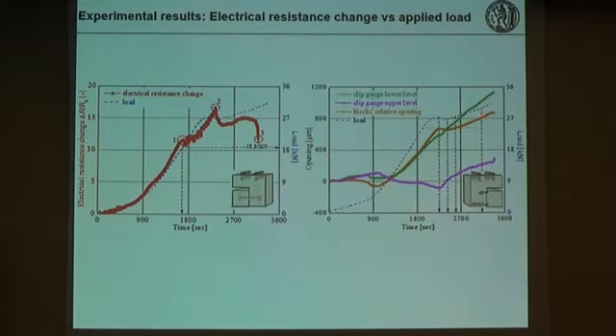And what I would like you to notice is that at the load of 27.5 kilonewtons, there is also a decrease in the displacement. What this means is that the two blocks are coming closer together. So the nano-reinforced mortar is coming closer together, and this can explain this decrease. So when the material is coming closer together, the electrical resistance is decreasing, while when we have tensile stresses, the electrical resistance is increasing.